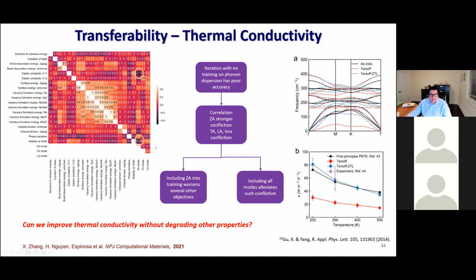But if you look at the next two modes, the in-plane modes, transverse and longitudinal, they are positively correlated. So one thing that you realize here is that you don't want to just put in the mode that didn't fit well, but all three modes will give you a better performance. And indeed, we were able to match thermal conductivity very well now without degrading too much the other properties.